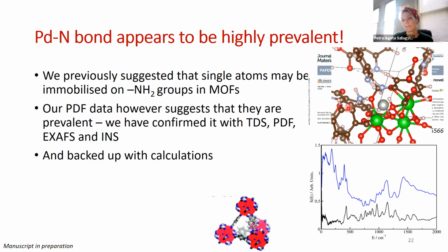But it is possible that they rotate so that the amino groups for every single linker are pointing inwards. And if it so happens, in particular when they're close to the corner, then they can pinch one palladium atom and immobilize it as a single naked neutral atom in here. That is actually quite a strong bond, as it turns out, and that fixates the structure as such, so the rotation becomes prohibited. And this is what we're finalizing at the moment for the phonon calculations.